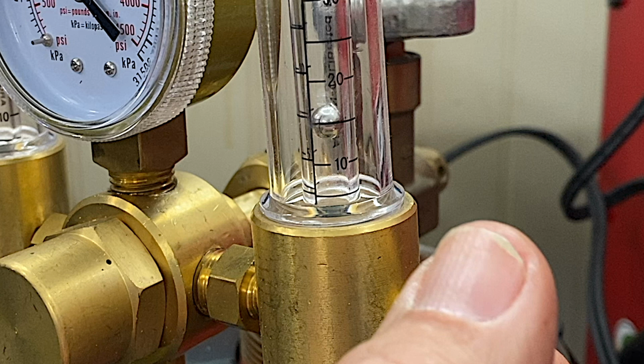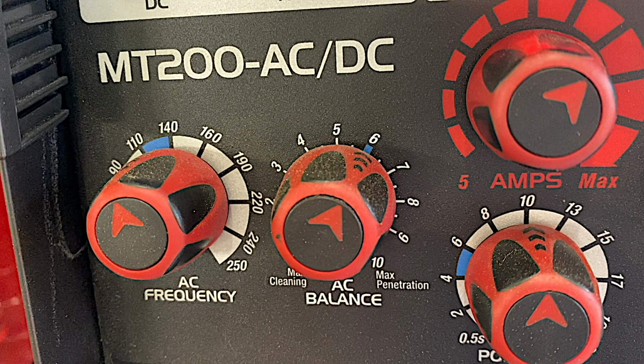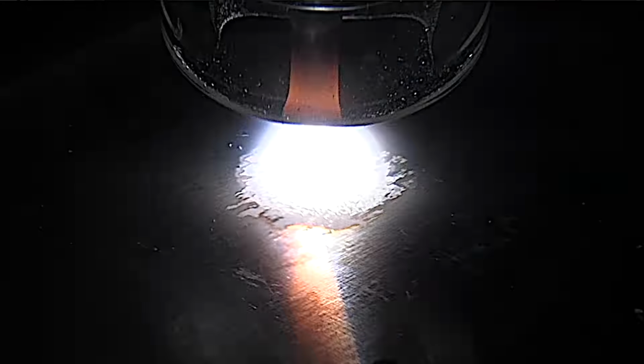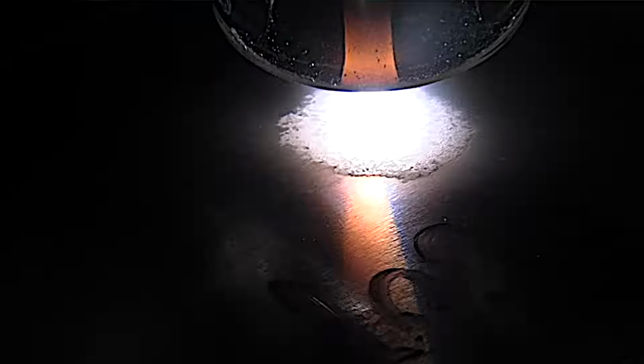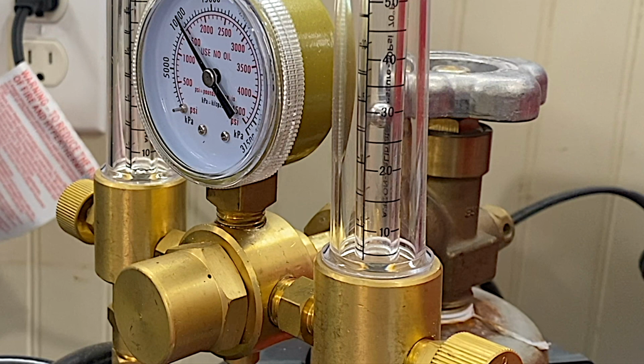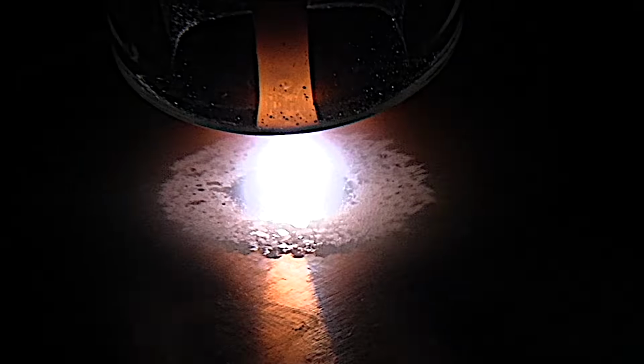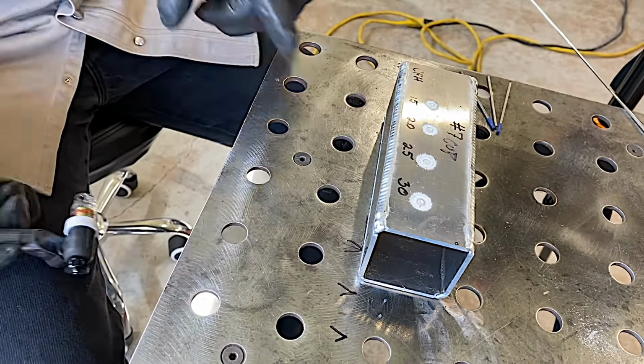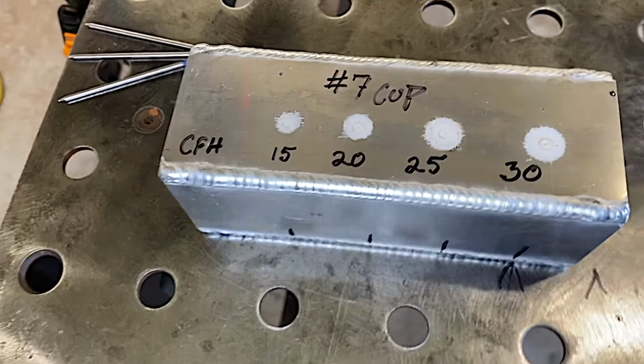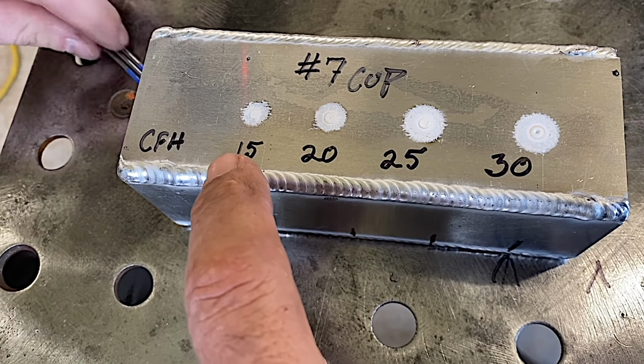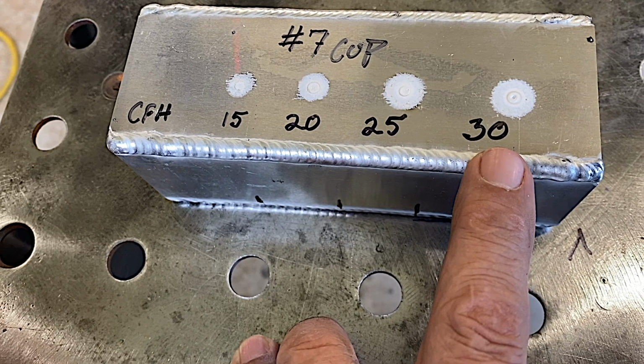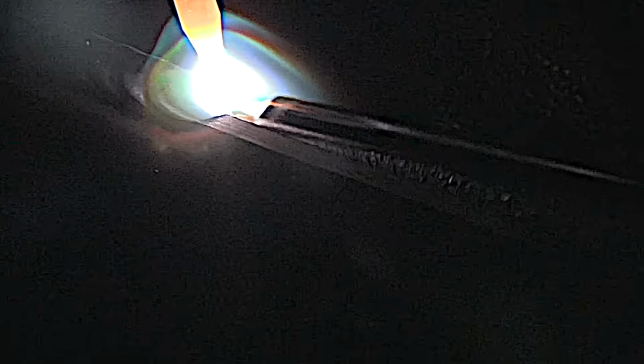Flow meters can vary. It depends on a lot of different things. It depends on how long your torch is and all that, and if you've got any restrictions in the line. But it's a good idea to test your argon flow no matter what cup you're using to make sure you're getting optimum cleaning for a given cup. Now in this case, I used a 7 cup, and I tested starting at 15 and going all the way up to 30 CFH in 5 CFH increments. And I didn't change anything on the machine, but the cleaning action, the cleaning path changed drastically. So I wound up settling in at somewhere between 25 and 30 CFH, and that gave me a lot cleaner puddle than the bead that I ran previously.